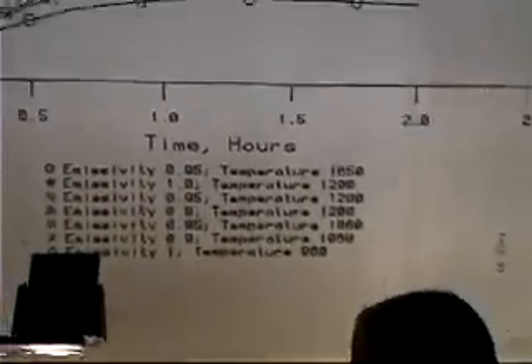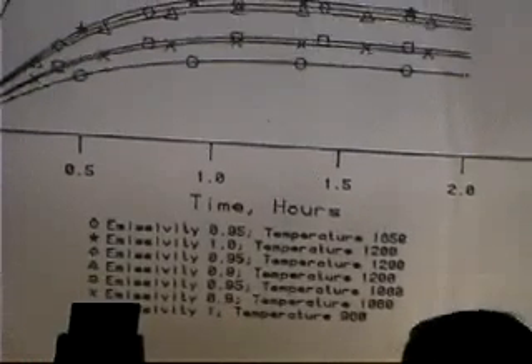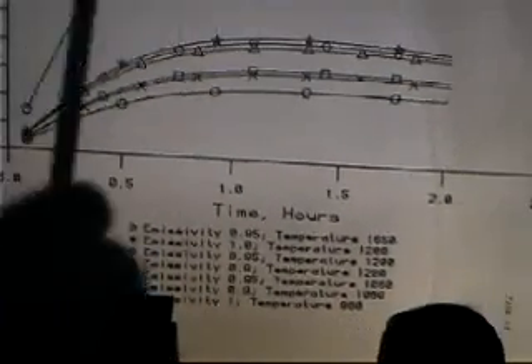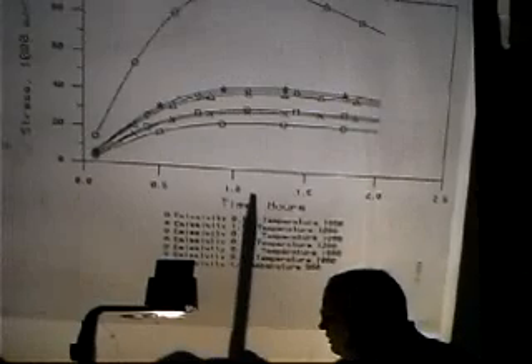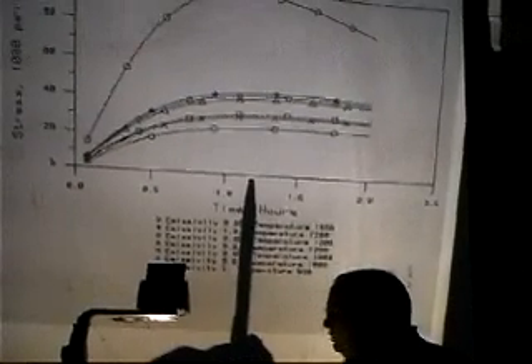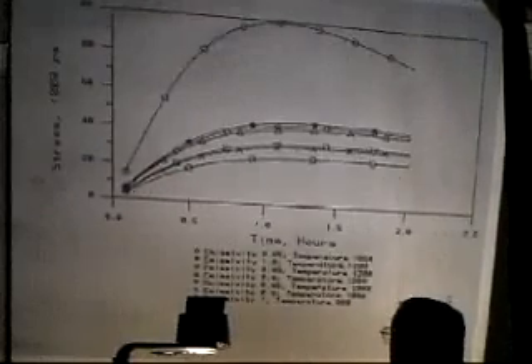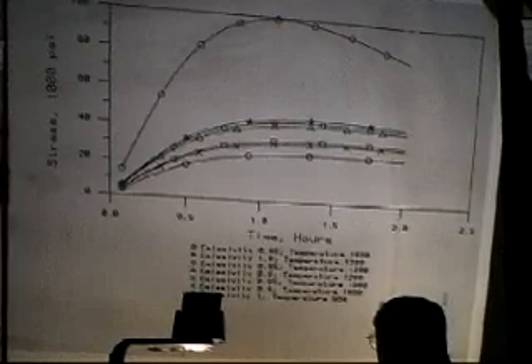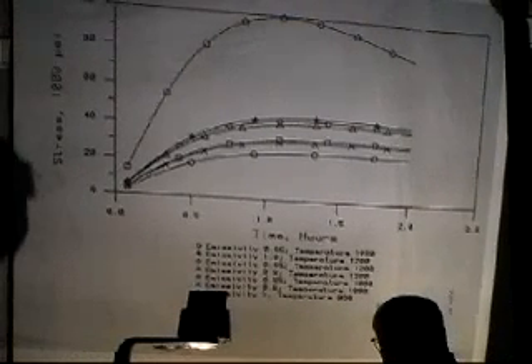It was the clink, the brittle fracture that occurred during heat treatment, that did this in. And you can calculate the types of stresses in the furnace. You have to assume the emissivity, because it's mostly radiation heat transfer, but we did all that. You can show that after about 1 hour in the furnace, you can get 100 KSI residual stresses in the center. That's sufficient, even in these types of steels, to cause the thing to fracture.